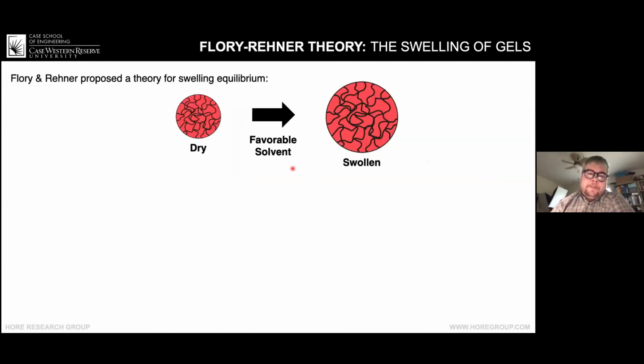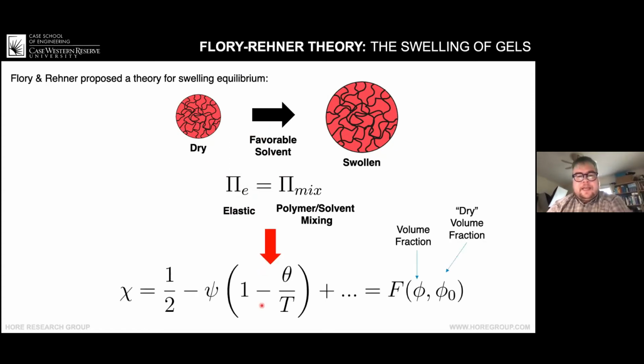So the Flory-Rehner theory is looking at a polymer gel or a polymer network that's put into a favorable solvent and then swells, I guess, to become a gel. And it results from setting the contributions to the osmotic pressure from the elastic component from all these chains to that of the polymer and solvent mixing together when it's placed into the solvent. So after some manipulation of the two expressions, you get the Flory-Huggins interaction parameter that you can express as 1/2 minus this coefficient here, times this quantity that depends on the theta temperature, the temperature of the solution, and then some higher order terms. And that's equal to some function that contains the volume fraction of polymer and the dry volume fraction. So what the volume fraction is like without any solvent.